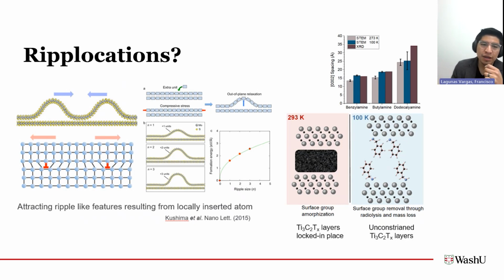One of the common ones is where you have a locally inserted layer, a locally inserted column of atoms, and you have this dislocation defect. Because of this locally inserted atom, you have this strain that occurs on this material, and these dislocation defects tend to repel one another. In 2D materials, you can imagine that if you locally insert an extra column of atoms, since these layers are free to move around, you'll introduce this buckling that occurs between these layers. And you see this ripple-like defect, and thus the term Ripplocations.